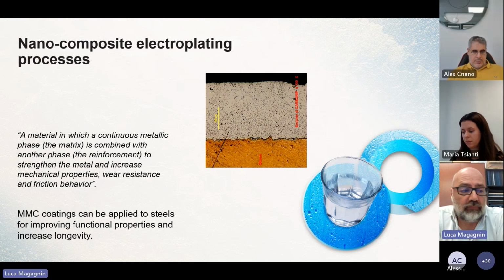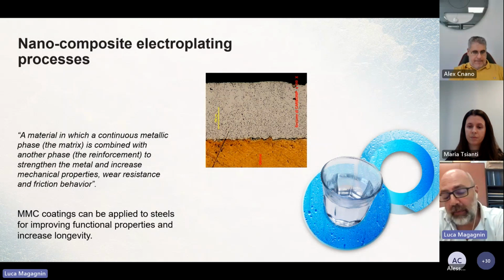For instance, we can imagine to co-deposit very hard ceramic particles, to increase a lot the hardness of the nickel matrix, which is typically not so high in comparison with the hard chromium. But with the use of the particles, especially at the nanoscale, the value of the hardness can match the one of the hard chromium. So in terms of wear resistance, for instance abrasion wear or erosion wear, the coating can be really competitive with the hard chromium.